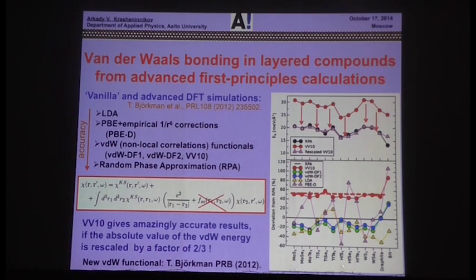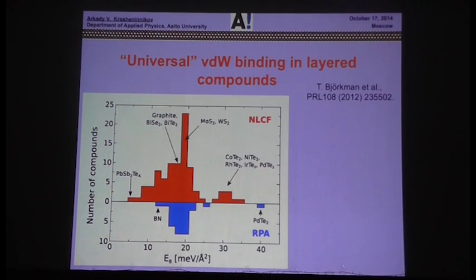Here I would like to remind you that standard density functional theory, basically LDA or GGA exchange-correlation functionals, doesn't account for van der Waals interaction. You should go beyond that, with different levels of sophistication. Making the long story short, we did some very thorough tests of which approach is good and which is not so good, and calculated van der Waals energy for a large number of materials. If you plot the number of compounds as a function of typical van der Waals energy between the layers, pretty much all the values fall in a very narrow range, which means that van der Waals interaction between layered materials is more or less universal. Whether you have metals or insulators, it's more or less in the very narrow range there.